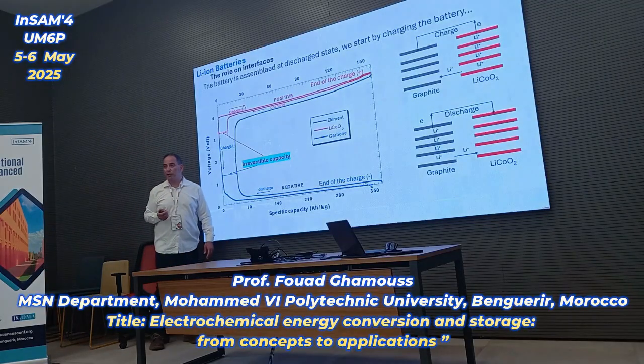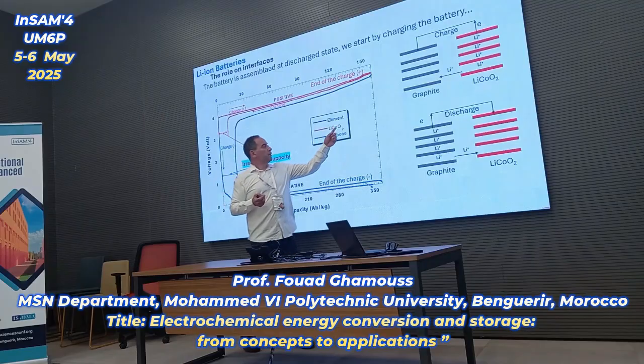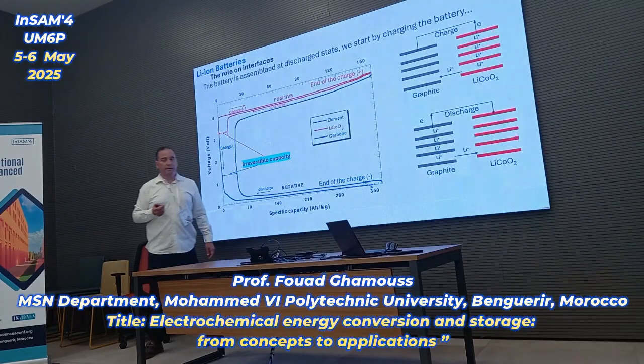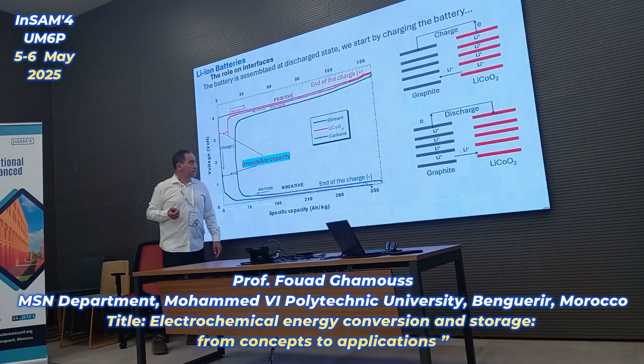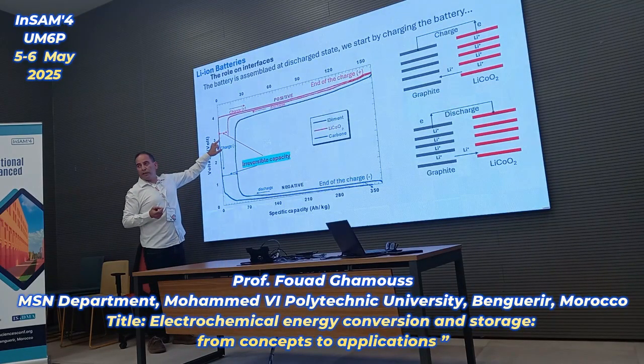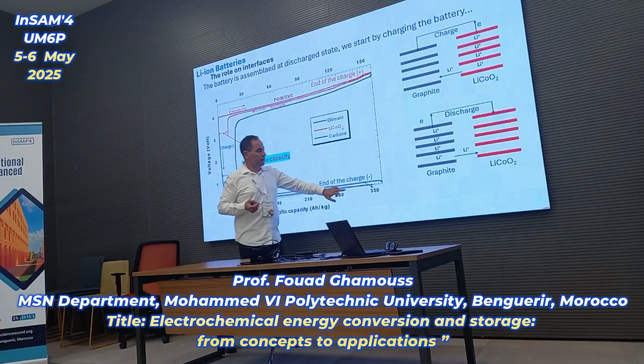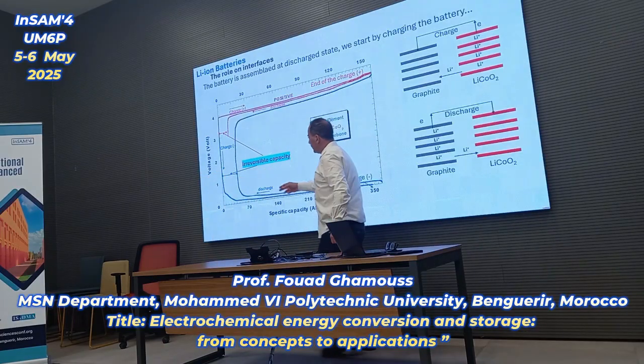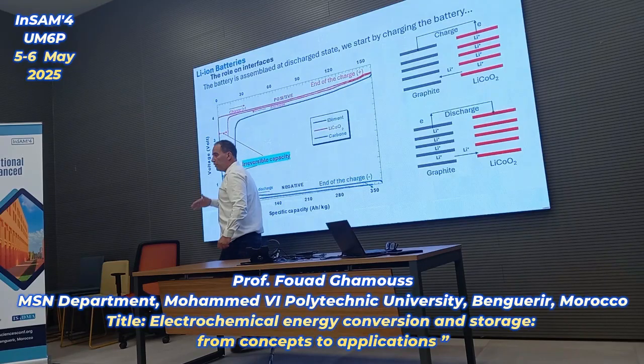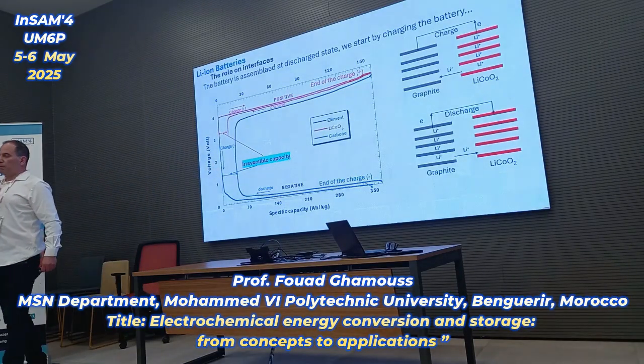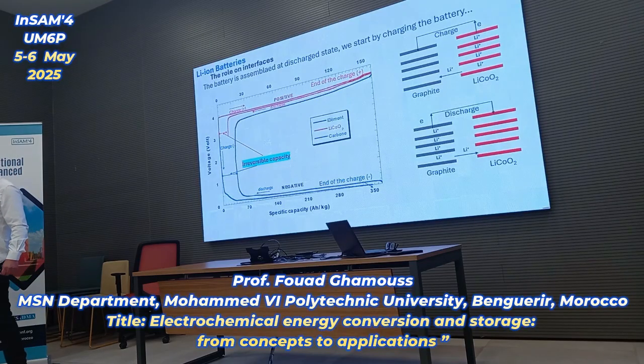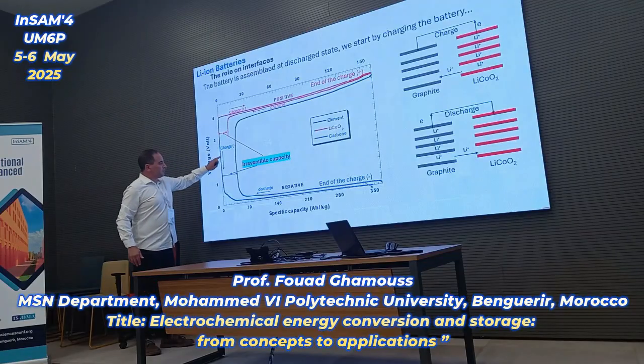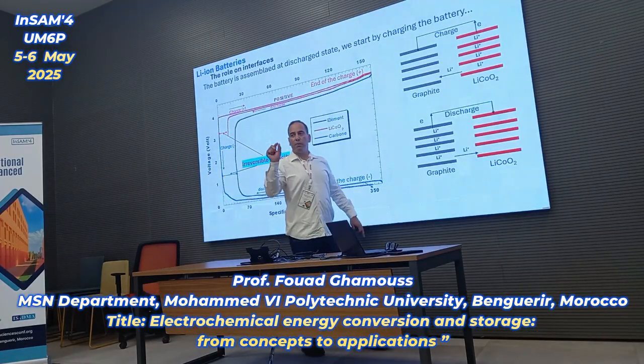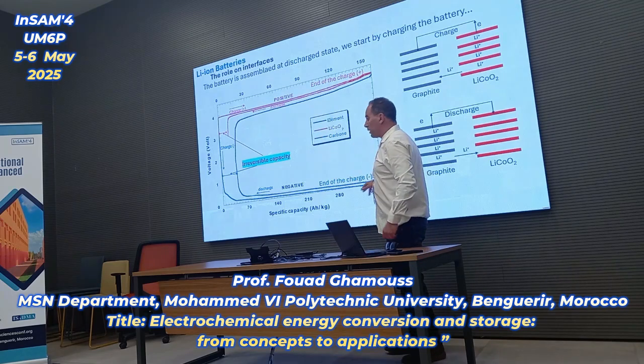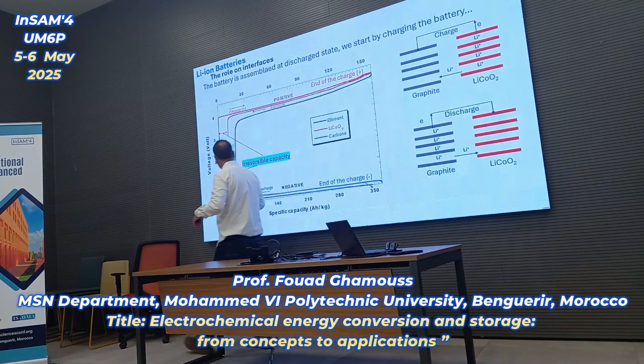So this is a figure that shows the first charge and discharge of a lithium-ion battery using lithium cobalt oxide as the cathode material and graphite as anode material. Starting the charge of both electrodes from the open circuit voltage here, in the blue color, the first charge of the graphite. And during the first charge of the graphite, you see that the potential decreases. And this happens because you are creating the lithiated graphite, which has a potential close to the lithium metal. So that's why the potential is decreasing until reaching almost zero versus lithium. So it becomes like lithium, almost the same potential.